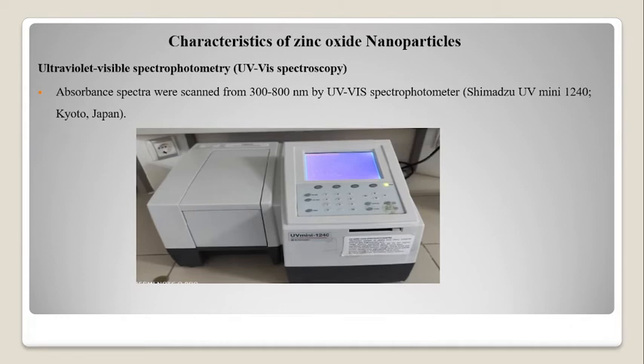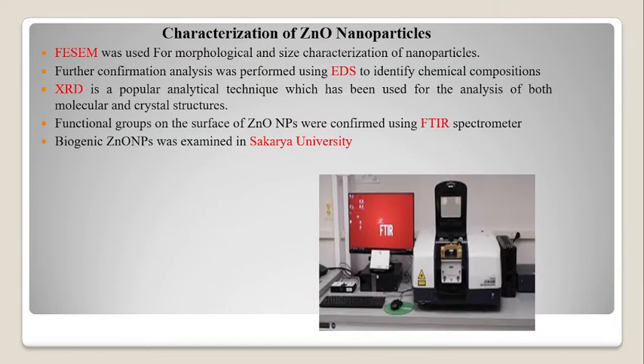For characterization of zinc oxide nanoparticles, all samples were scanned from 300 to 800 nanometers. For morphological and size characterization, we used FESEM and EDS. After that, XRD analysis was used for detection of the crystalline structure, and finally we used an FTIR spectrometer for detection of the functional groups.